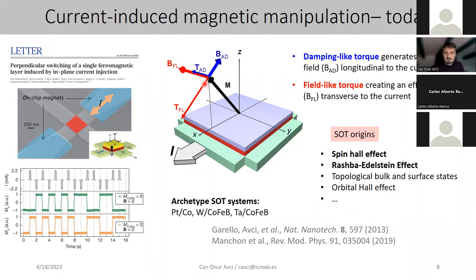The arrows show the effective field and the torque direction. Damping-like torque can exert torque on the magnetization based on physical phenomena such as the spin Hall effect, the Rashba-Edelstein effect, or topological bulk and surface states in certain materials, or more recently the orbital Hall effect. The first discovery of this kind of experiment dates back to 2011 on a simple bilayer system of platinum cobalt with some oxide capping. But nowadays there is a large amount of literature that you can read about spin-orbit torque magnetization switching, or control of magnetization or domain wall motion.